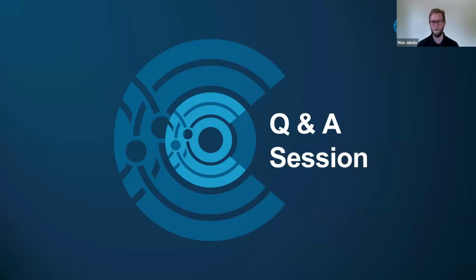So that will demand that we are able to model all the layers below with very high accuracy. And the reason why is that, let's say that our optical model is not able to super accurately model what is underneath this thin surface layer of interest. There's going to be some mismatch between what we've modeled and what we've measured. And the problem is, we know that a very thin surface layer is just going to induce a small shift in the measured spectrum. And so what that means is the sensitivity of our model while fitting to the measured data is going to be dominated by what it's missing in terms of modeling the lower layers than actually what is caused by the surface layer. So the quick answer is that it is doable, but it requires really good optical modeling of the layers that you have below the surface layer.